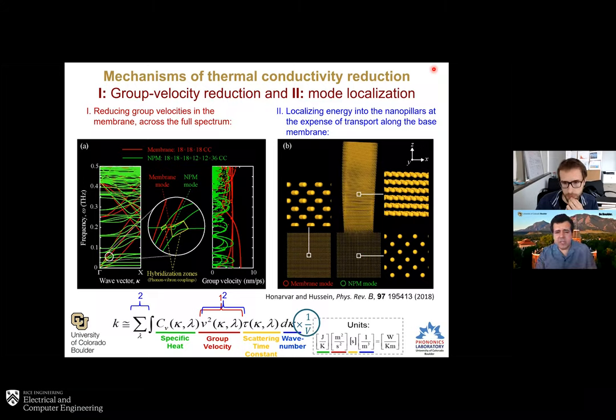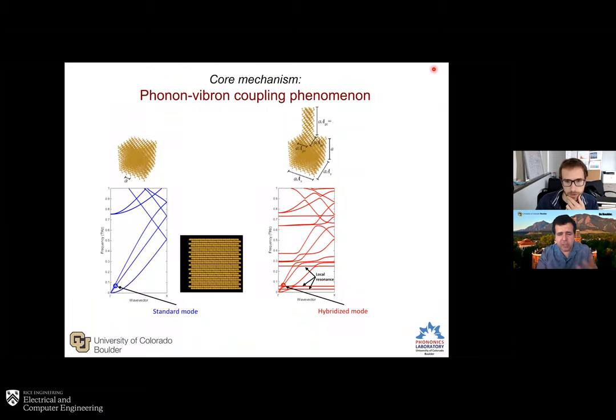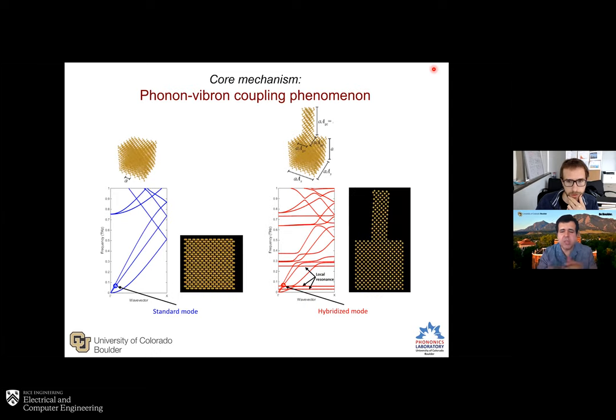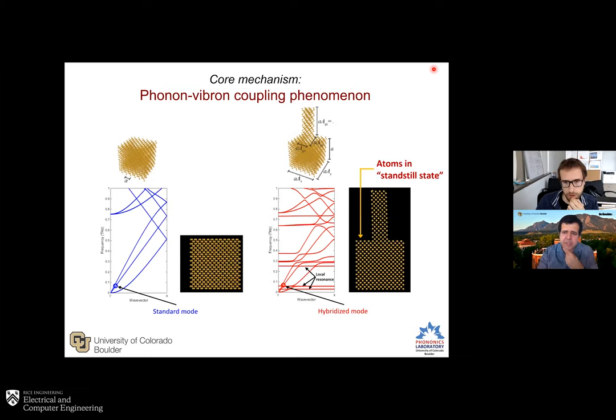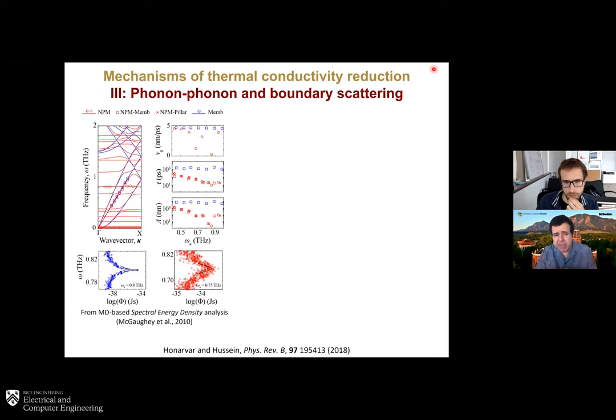All right, so this is just a video to show you what I've just shown you in a static picture. This is a standard mode, and then that same mode is rendered totally stationary, totally localized because of that local resonance coupling effect. So atoms in standstill state in the base membrane. So these were the two main mechanisms, but I should also say there's a third one, and that's to do with the phonon-phonon scattering and also any boundary scattering that might arise on the surfaces of the membrane.